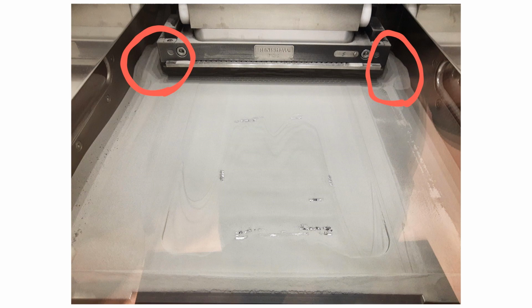Earlier on, if you remember, we talked about in the early days of aviation, maybe 80% of failures were down to the machines. And this particular failure, I think, illustrates how additive is maybe somewhere in between those early days of aviation and the more mature aviation industry we have now. So we came in to find the machine in this condition where there's a lack of powder all at the front here. This is a catastrophic failure. And it's not that we're actually out of powder. There is still powder in this hopper here.